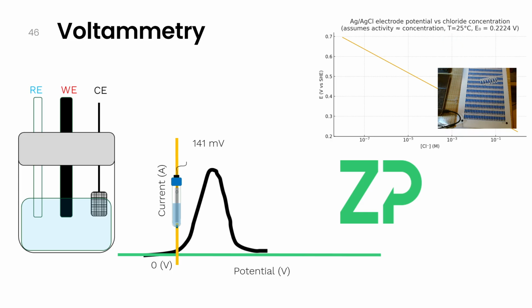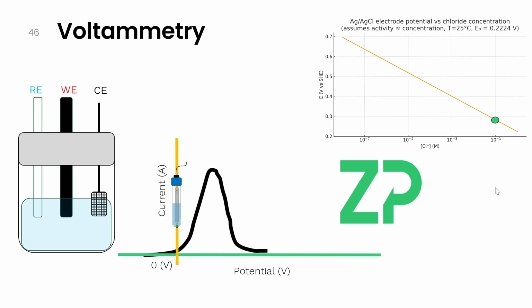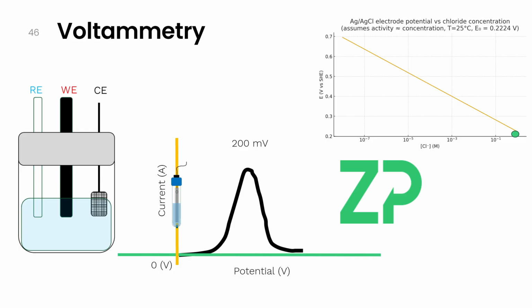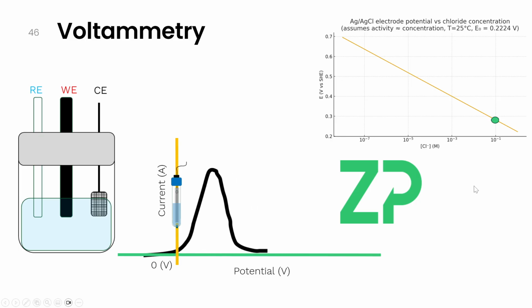I realize that if I just turn these off for a second, I might run that thought experiment one more time for you. So 200 millivolts because I've got 1 molar chloride in my reference electrode, but if I was to dilute the chloride by 10x, then the reference potential would also shift, and that means that peak would also shift by approximately 59 millivolts. We go from 200 millivolts to something like 141 millivolts.